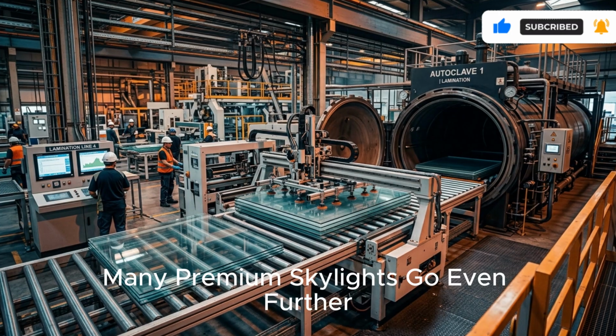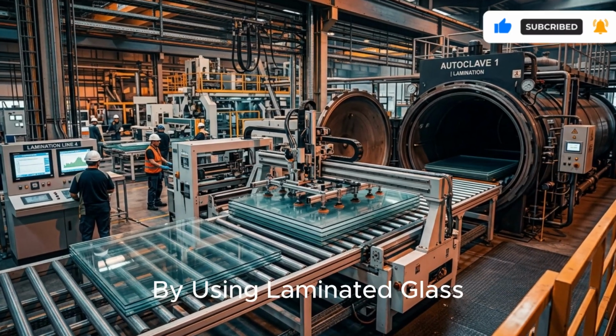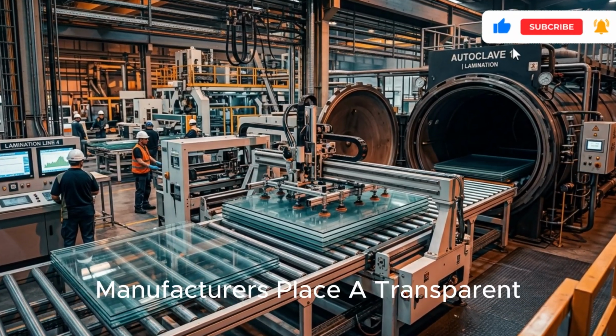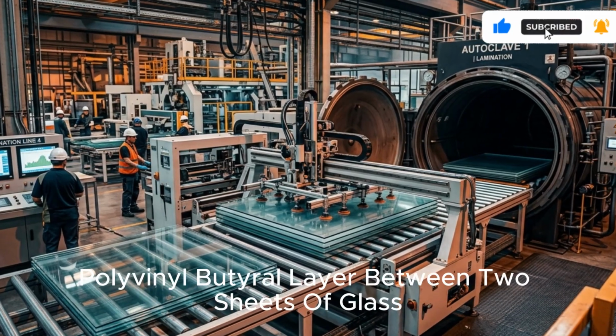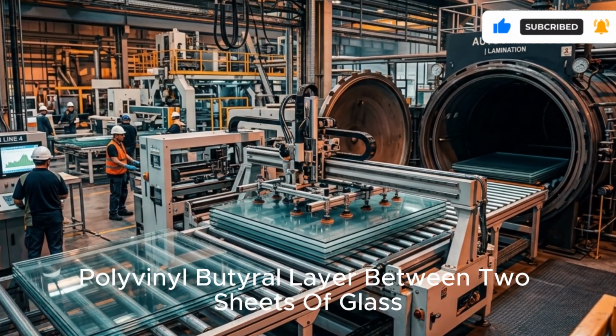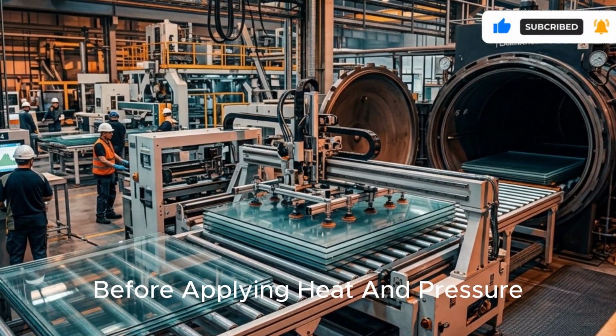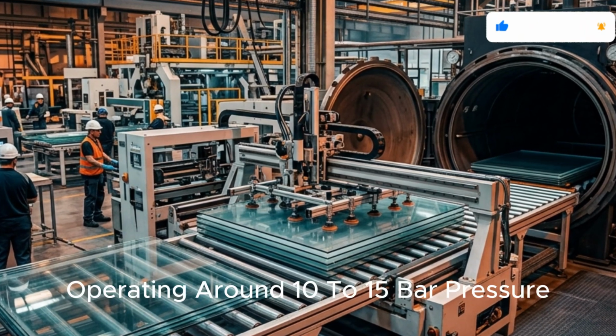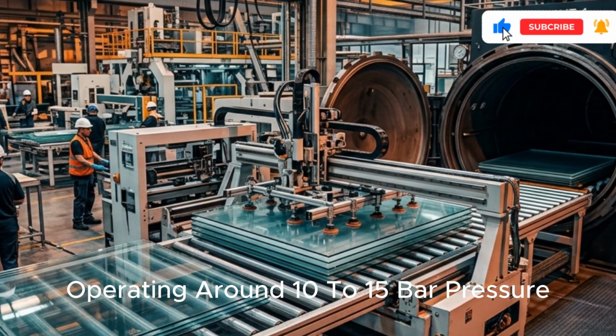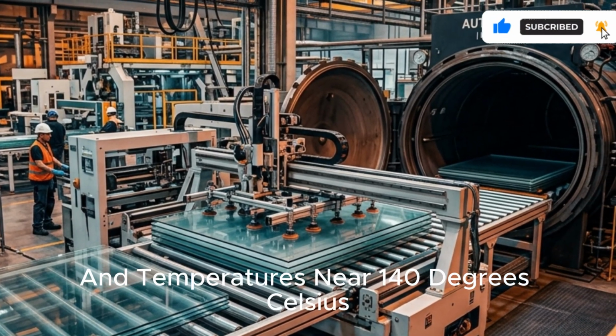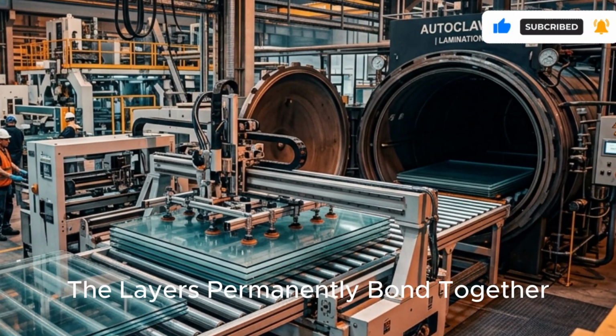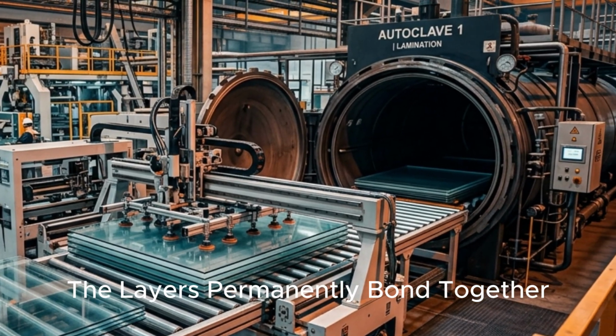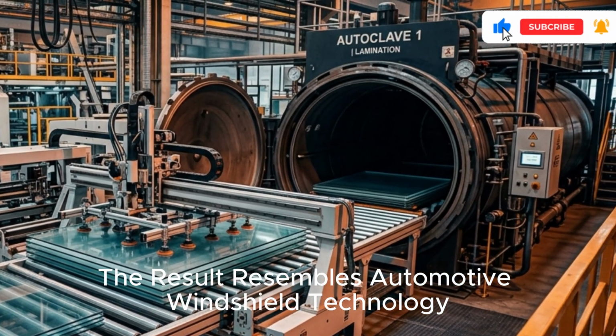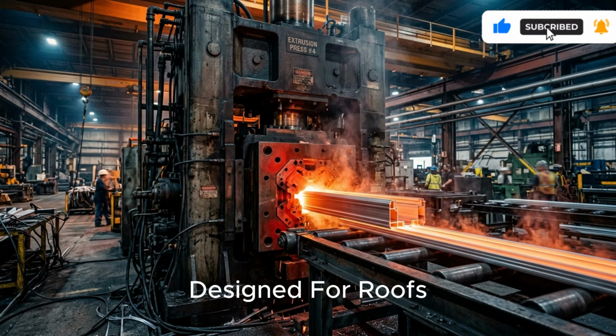Many premium skylights go even further by using laminated glass. Manufacturers place a transparent polyvinyl butyral layer between 2 sheets of glass before applying heat and pressure. Inside an autoclave operating around 10 to 15 bar pressure and temperatures near 140 degrees Celsius, the layers permanently bond together. The result resembles automotive windshield technology designed for roofs.